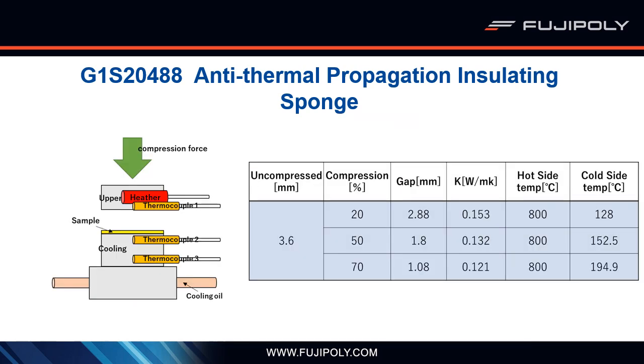Measuring accurate thermal resistance with a lot of these testers can be a challenge because of heat loss when you're running a hot side temperature that's hundreds of degrees Celsius. So the chance of getting heat loss can definitely impact how accurate your measurements are. But we tried our best to come up with some kind of a value, at least early on. And you can see those on the screen. But depending again on the compression value, you're going to end up with a different number. So the more you compress the material, obviously you're going to change that. Now from 20% to 70% compression, the thermal conductivity ranges from about 0.121 to about 0.153. So fairly high resistance material. So again, with that and the transient response of the material, we believe it's a very good candidate material for insulating batteries or other types of heat sources.